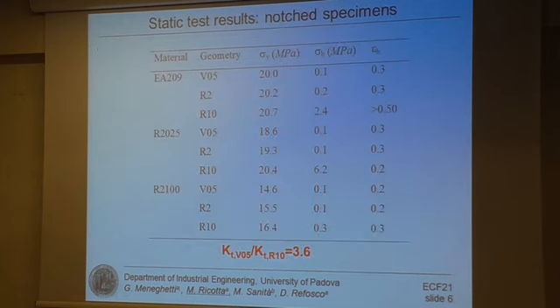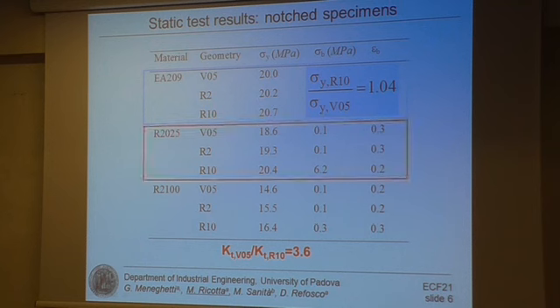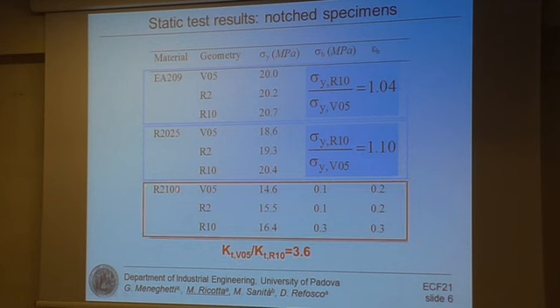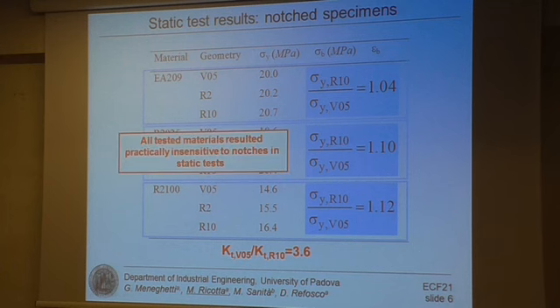The results of static tests carried out on notched specimens are summarized in this table. Keeping in mind that the ratio between the theoretical stress concentration factor evaluated in the case of sharp notch with respect to that evaluated in the case of blunt notch is equal to 3.6, we can see here that for the compound made by virgin polypropylene, the ratio between the yield strength evaluated in the case of blunt notch with respect to the yield strength evaluated in the case of sharp notch is equal to 1.04. Similarly, in the case of partially recycled polypropylene, the same ratio is equal to 1.1. And finally, also in the case of totally recycled polypropylene, the same ratio is equal to 1.12. Therefore, at least from an engineering point of view, we can conclude that all tested materials resulted practically insensitive to notches under static loads.